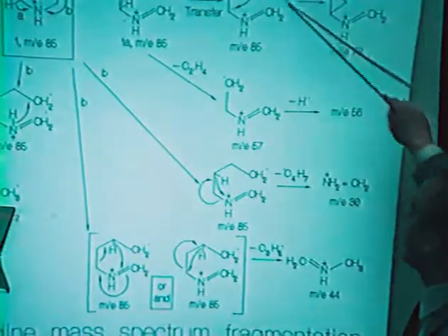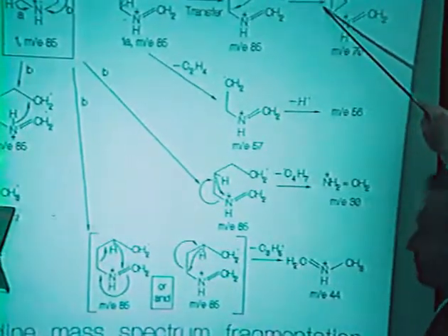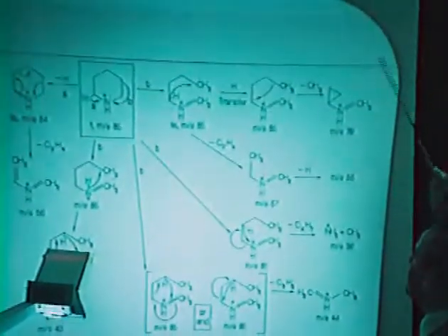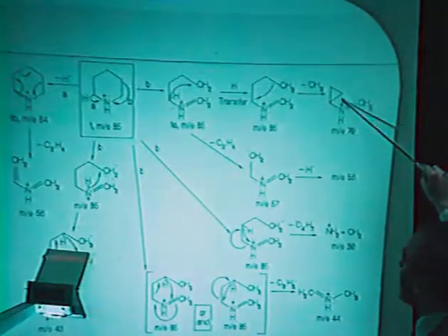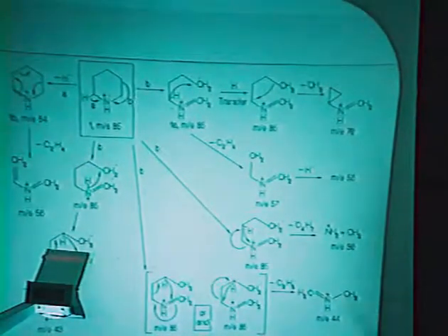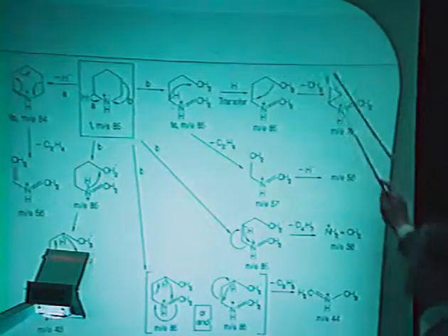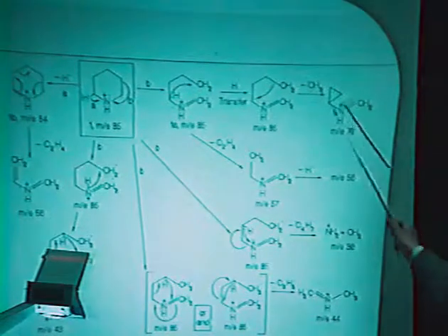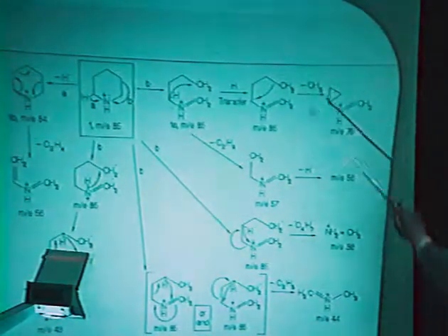We see a release of a methyl group in the beta position, and the gamma group is still in there. We should have seen 70. It didn't occur. So what it's telling us is that the D2 has been exchanged with the proton coming from the beta position.